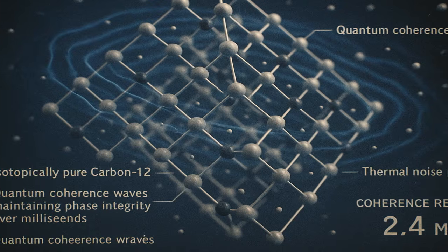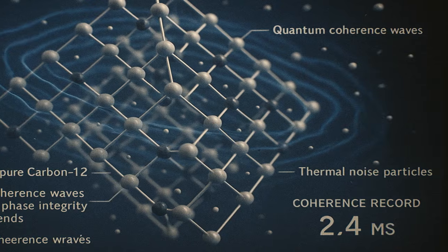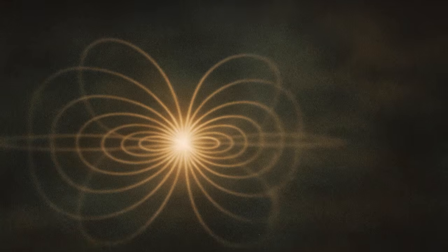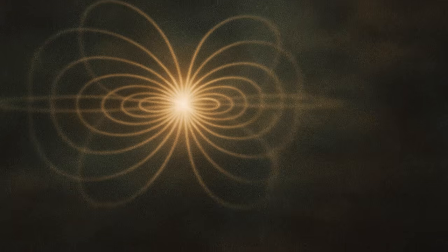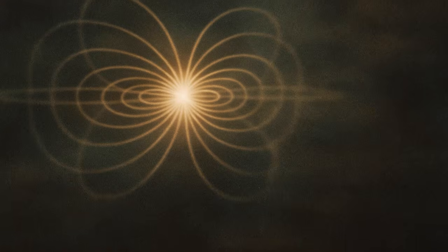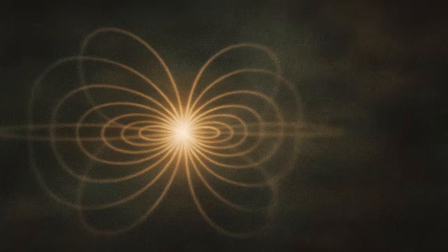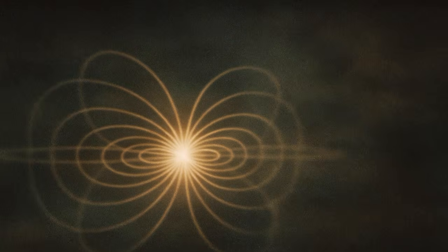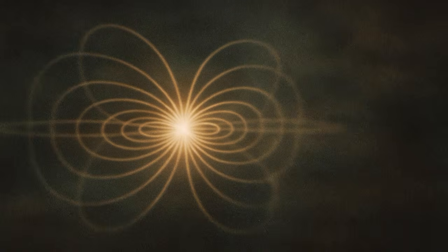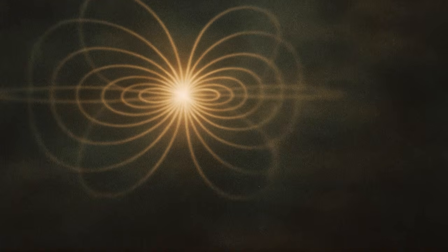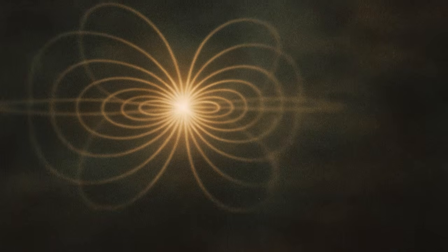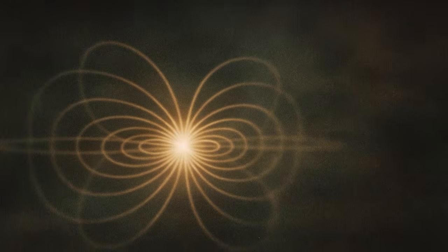The quantum coherence is the real trick. The electron spin in the NV negative ground state splits into 3 levels. M sub s equals 0, plus 1, minus 1. 0 sits lower by 2.87 gigahertz at 0 magnetic field. That splitting comes from spin-spin interaction. No magnetic field needed. Hit the center with a 532 nanometer laser, and you optically pump it into the M sub s equals 0 state.